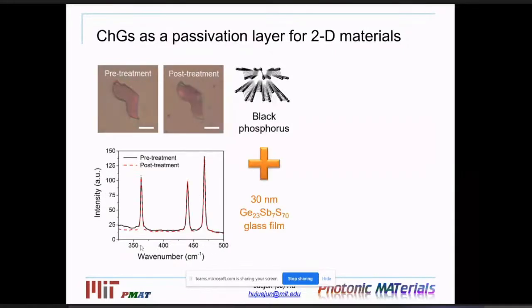Now, if you coat it with a thin layer of chalcogenide glass film, then this material can actually even withstand very strong oxidants, such as hydrogen peroxide. After putting the coating on, we exposed the material to hydrogen peroxide, and there's essentially no change in the Raman spectrum here, showing that this coating of chalcogenide glasses can indeed stabilize this chemically unstable black phosphorus material.